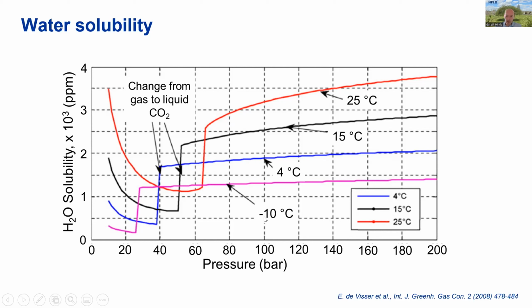So typical operating pressure, this is a plot of the solubility of water in dense phase CO2 and in gas phase CO2 on the left-hand side. You can see the transition in solubility when the CO2 changes from the gas phase on the left to the liquid phase on the right. And typically the CO2 is transported in the liquid phase. So here at 100 bar and 25 degrees Celsius, for example, the solubility is just over 3,000 parts per million.